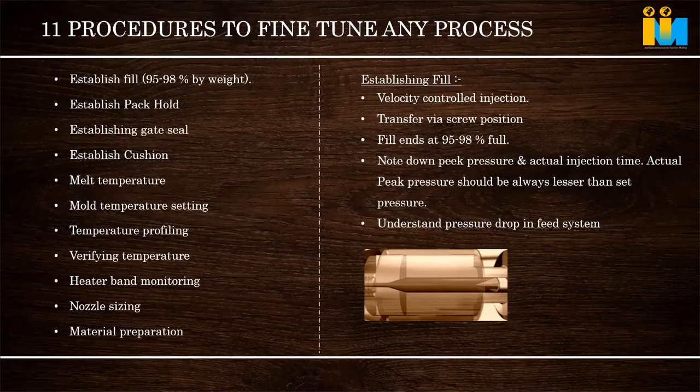In that, there is a micro stop happening in the molding, so we have to understand this. To get better repeatability of the part, we have to inject 95 to 98% of the part by weight in the injection phase. In the molding shop, people sometimes do this in holding also. We need to understand what a real switchover position is. Establishing the correct switchover position based on the weight of the part is very, very critical for a repeatable process, shot to shot repeatability.